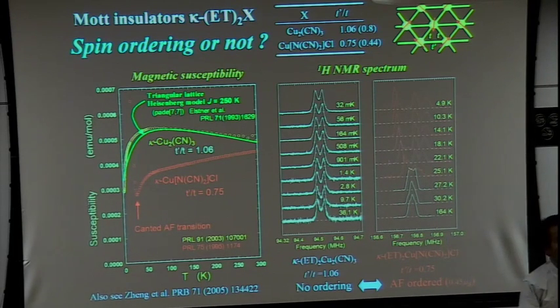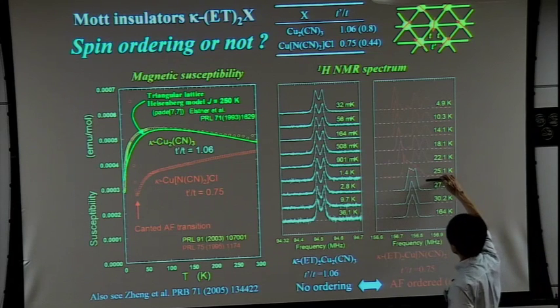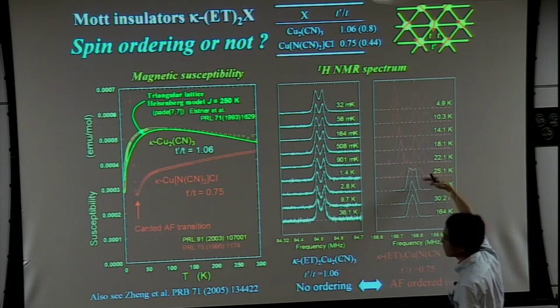The Knight shift is proportional to the susceptibility, going back to zero. Yes, the RVB state is a candidate. In this ordered case, which is metallic, the magnetization is staggered. So magnetic ordering occurs here, and this is clear indication.